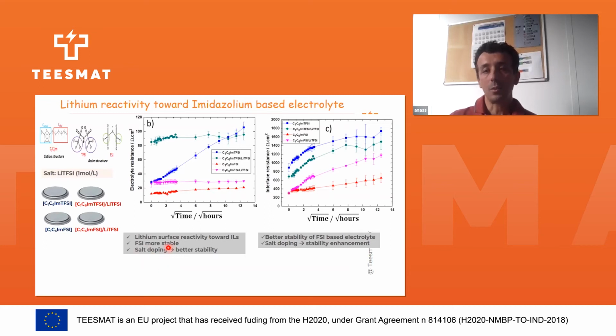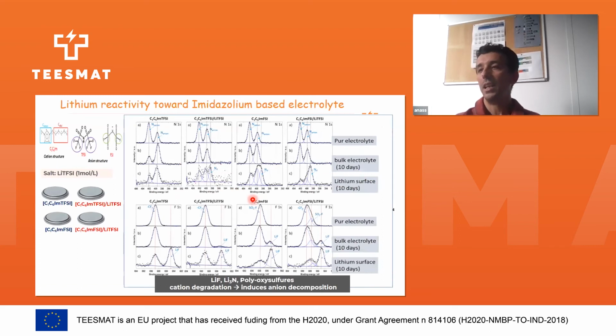And when we add salt, for example here I give the case of C1C6ImTFSI, we have degradation upon time of the lithium surface for this kind of electrolyte. But when we add LiTFSI to this electrolyte, the electrolyte resistance becomes stable. So the salt plays some role, and we will see later how XPS can explain this and link to this kind of information. So we performed XPS at the surface of lithium metal after aging.